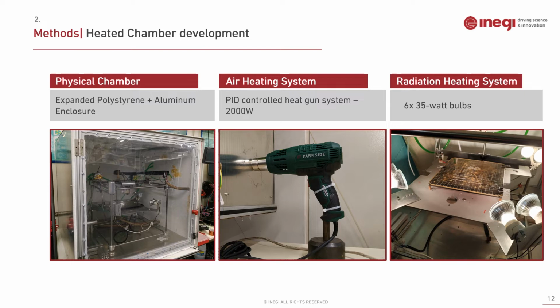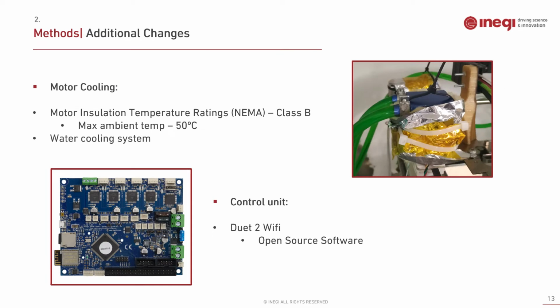The second part was developing a PID control heating system using a heat gun which pumps air at around 300 Celsius degrees into the chamber. And finally, we added a radiation system using 6 35-watt bulbs as shown in the figure to provide some extra surface temperature in the produced part. Finally, there were two other major changes required.